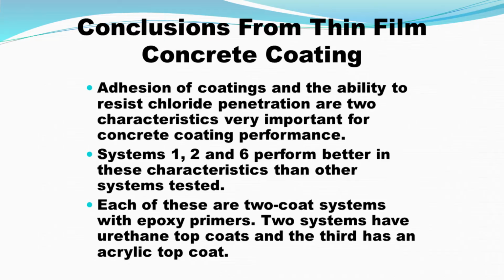In the study, the adhesion really didn't become an issue. All the coating systems showed significant adhesion to bond to the concrete and give you long-term performance from an adhesion standpoint. Systems 1, 2, and 6 performed, from the graphic, with a significant increase in performance from chloride ion penetration resistance.